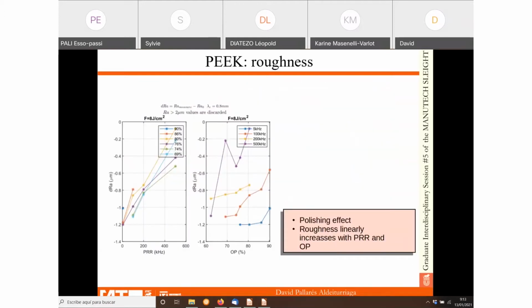Okay, here are also results of the roughness. We see a linear tendency that increases with repetition rate. There is an increment with overlap. Okay, as this is negative because it's the roughness change, we see the polishing effect that we were already seeing.